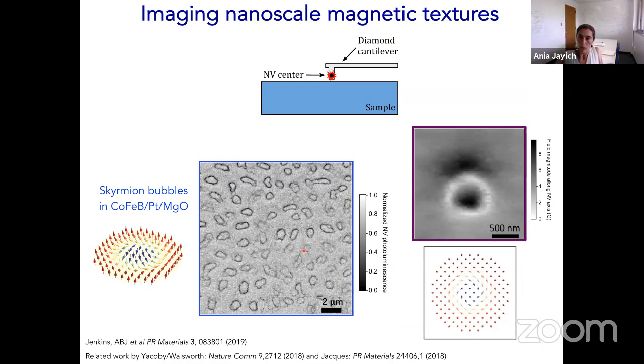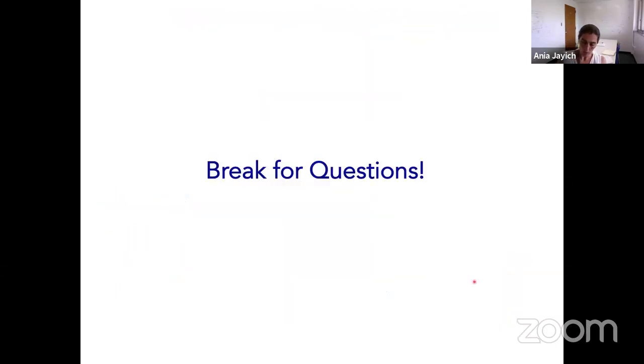We were also able to image a single skyrmion here, and using our ability to back out the spin texture within the material, we have plotted here what the spins are actually doing, which tells you some interesting physics about what's called the helicity angle and how these spins are rotating in these structures. So this just gives you two examples of the types of systems that we've been able to probe with our NV magnetometer.